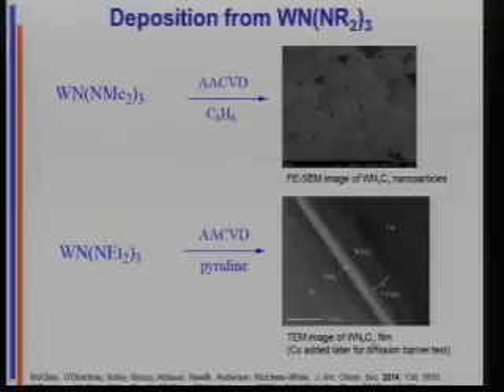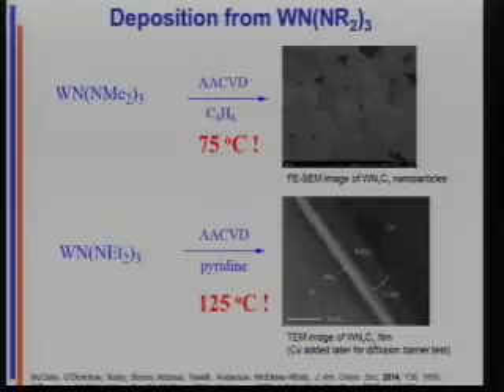And we do this at low temperatures, except we've entirely rewritten the book on what low temperature means. 400? I don't think so. 75 for the nanoparticles, and 125 degrees C, we can grow films that pass the diffusion barrier test, okay? And so that means that we've taken the CVD of these materials from the realm where you have to think, oh, we can do this on silicon, we can do it on glass. At 125, we could do this on organic electronics. You know, we could do it on polymers, all kinds of things, because we've been able to drop the temperature down into a range that's just unheard of for this kind of chemistry.